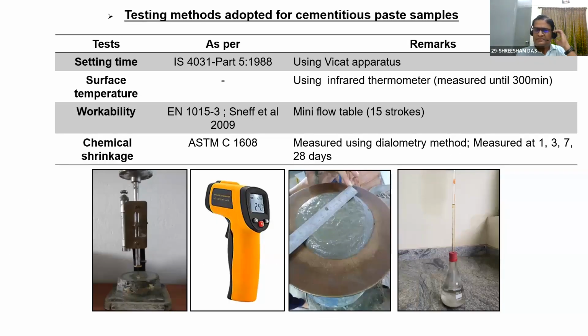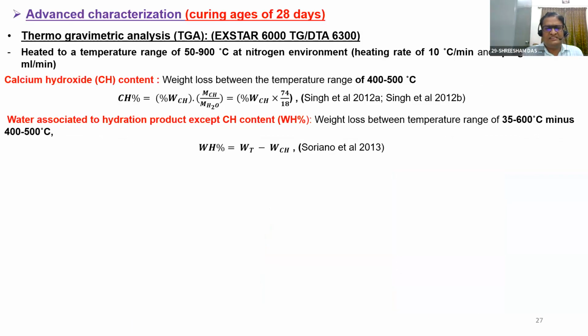This is the way the paste was characterized. First we characterize the paste, and then we did the advanced characterization. As I was saying about how we realized it is stopping the hydration, that is through the thermogravimetric analysis, that is TGA. If you do a TGA of a cementitious composite, you can understand how the hydration phenomena happens. We have two compounds, calcium silicate hydrates and calcium hydroxide. If you can measure the CH, that is calcium hydroxide, and the water loss, that is nothing but my CSH, you can tell how the hydration phenomena is happening.